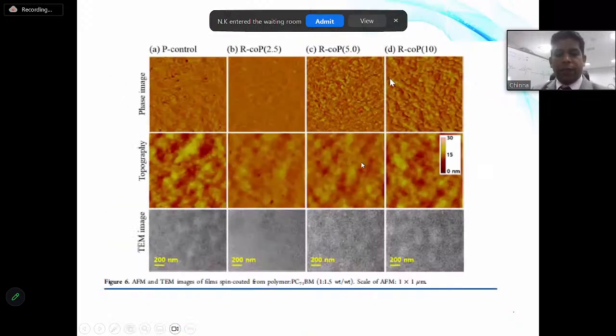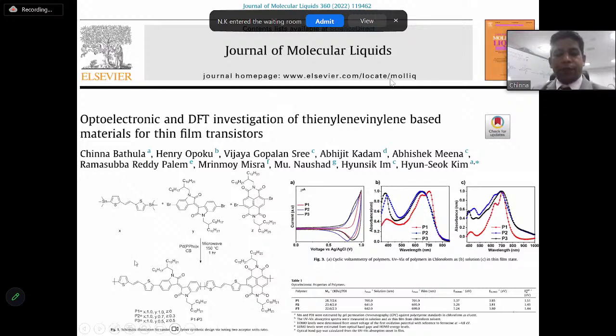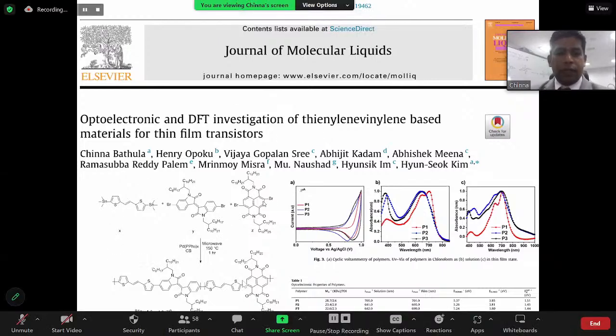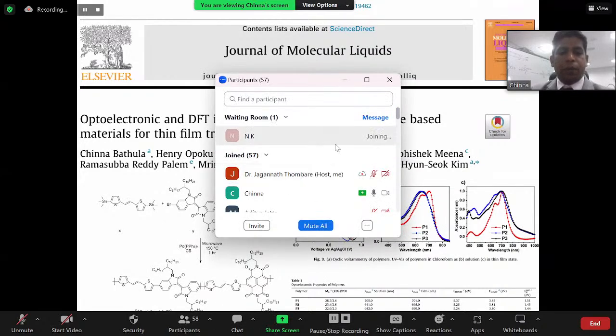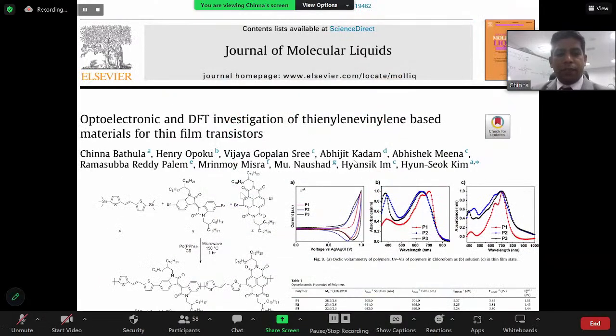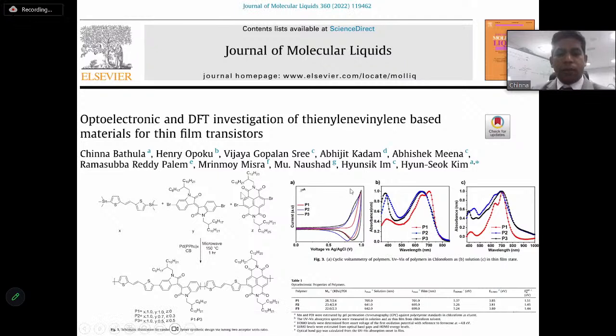And again, the AFM is clearly showing that when we use 5% of the additive material, the morphology is better. And these are the thin film transistors we prepared, with what are called random copolymers, or using a third component in the polymer backbone. So here we studied all the optoelectronic properties, and the interesting thing was that when we add the other component to the pristine material, the mobility has increased. So this is concept-based results rather than high mobility.